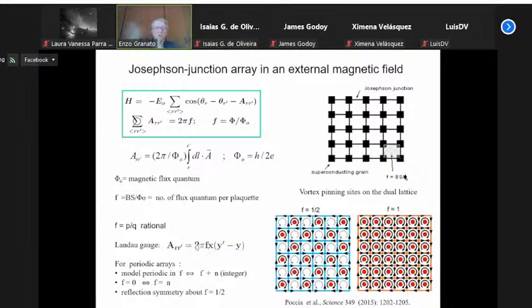So in particular, for example, for f equal to 1/2, this gives rise to a phase shift equal to 2 pi and pi. So there is a periodicity of 2 that translates, in terms of the vortices of currents, into having a vortex at each other plaquette, as indicated here by the red symbols. So for the 1/2 case, we have the double degeneracy, which arises because there is a periodicity of 2 for the line integral of the vector potential.